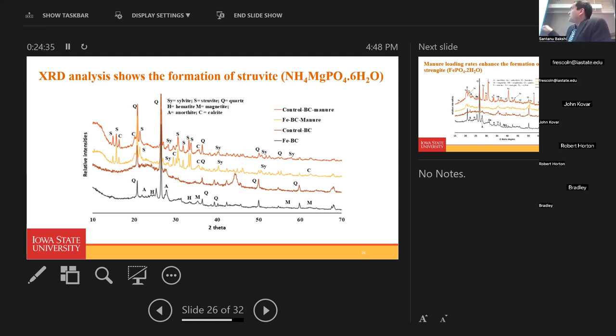Please note that in how we make the sample, we have a constant amount of biochar and we added sequential additions of manure. In that case, we probably have washed out most of the iron from the system. That's why the manure phosphate preferentially got absorbed on the magnesium phase.